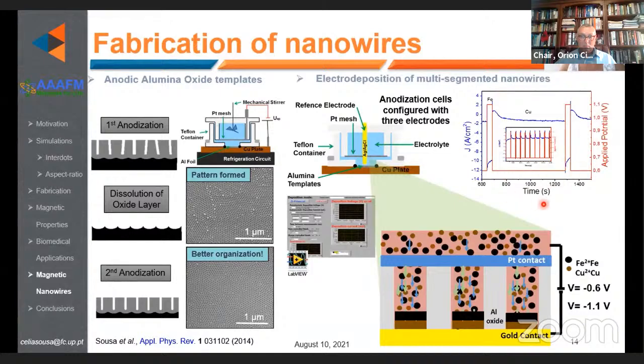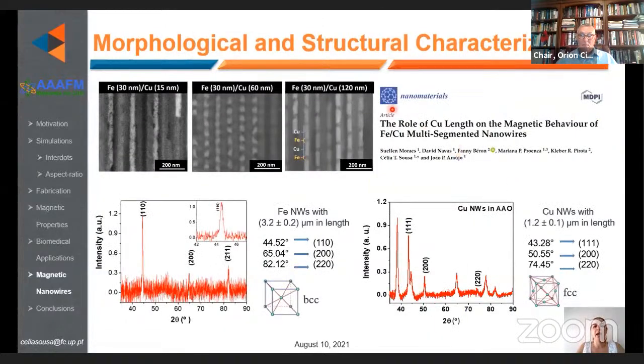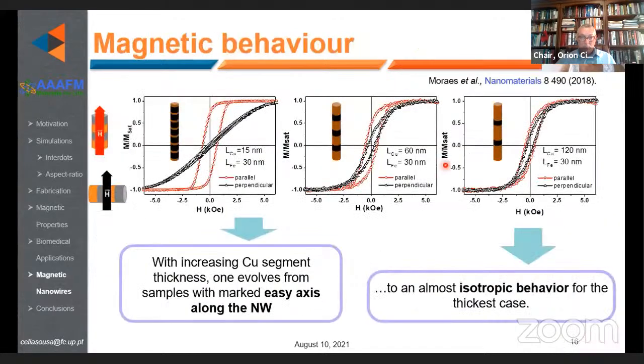The electrodeposition behavior was monitored for each layer of both materials. And as we can see here in these scanning electron microscopy images, we are able to deposit iron-copper multi-layered nanowires, and we are also able to change the length of the nanowires depending on the electrodeposition time. So we performed the structural characterization of these nanostructures, and we obtained for the iron nanowires a BCC structure with a preferential direction along the 110 direction.